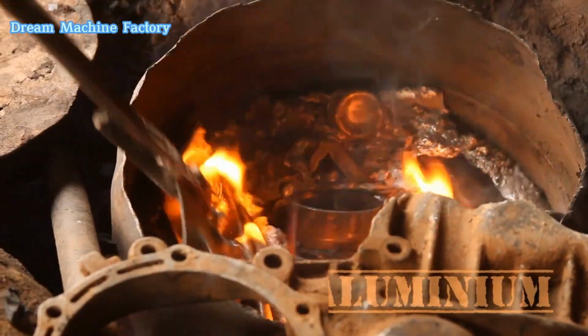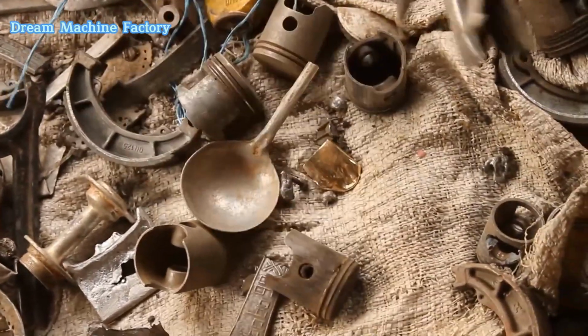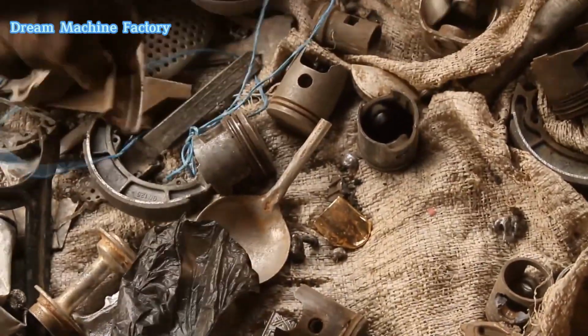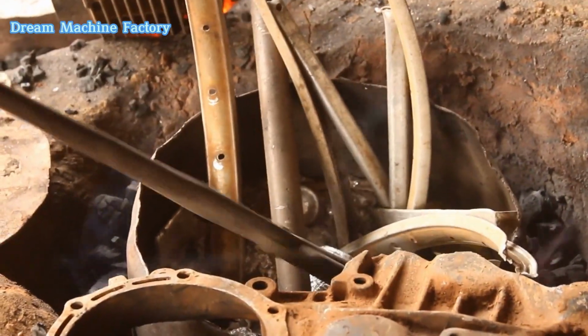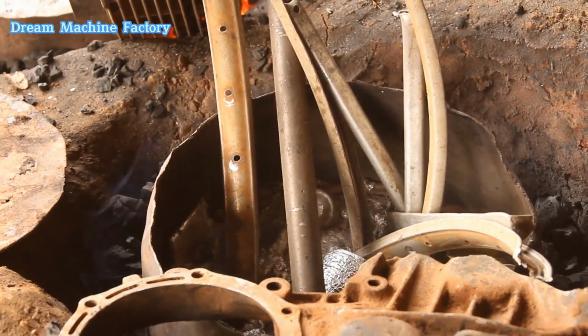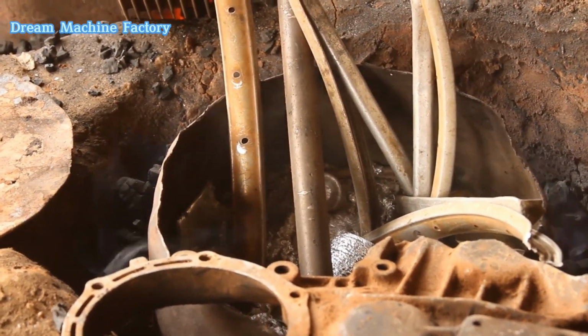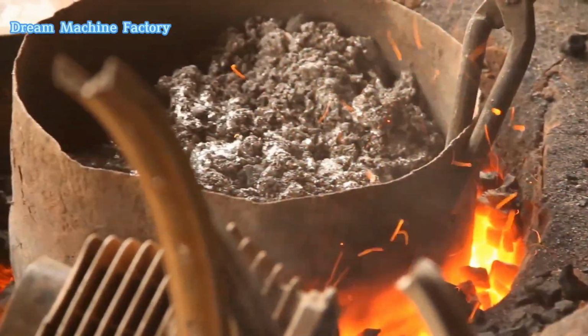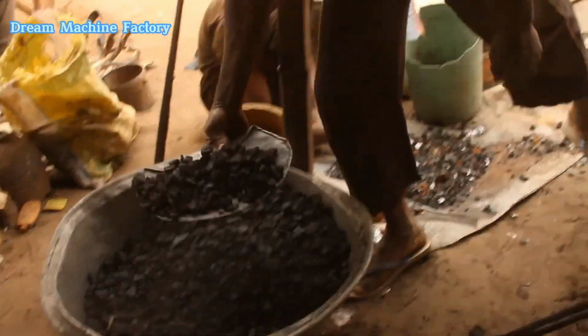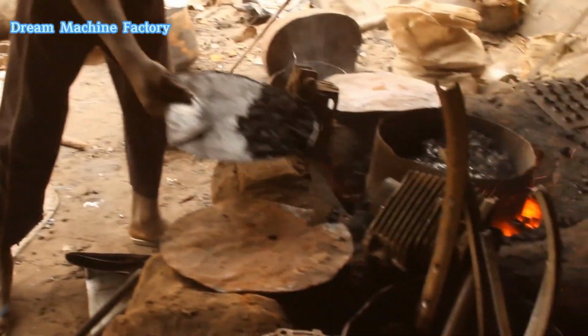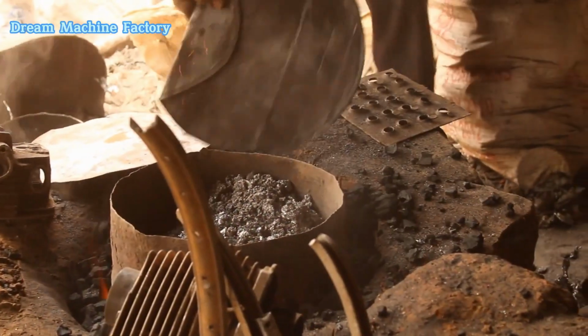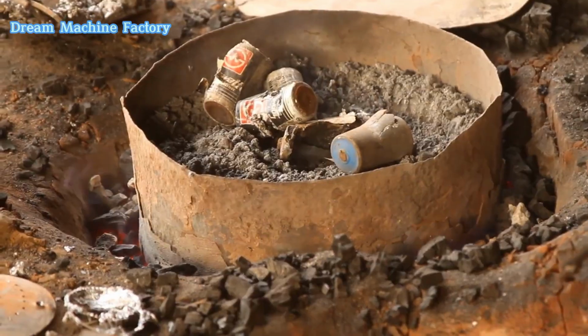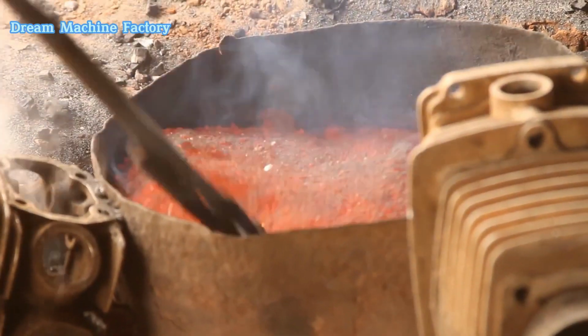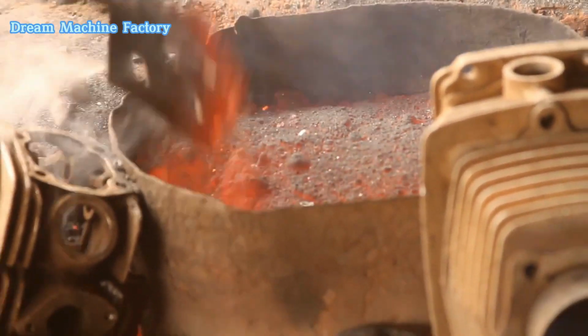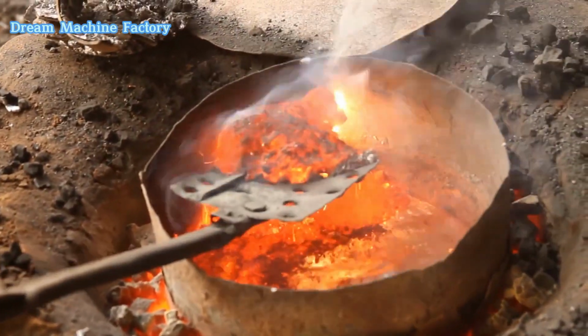Once the mold is prepared, the next crucial step is melting the aluminum. Artisans collect scrap aluminum from old engine parts, cans, and other discarded materials. These metal pieces are broken down into smaller chunks to ensure even melting. The aluminum is then placed in a crucible, a heat-resistant container, and heated in a traditional furnace fueled by charcoal or wood. The furnace reaches temperatures above 660 degrees Celsius, 1,220 degrees Fahrenheit, the melting point of aluminum.